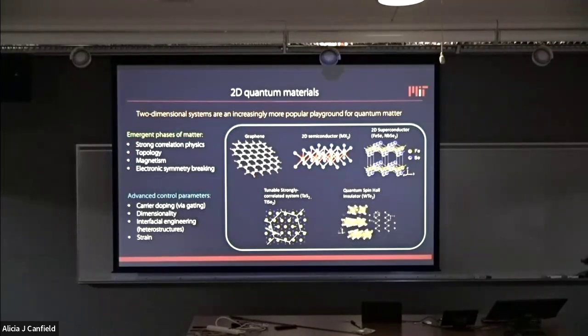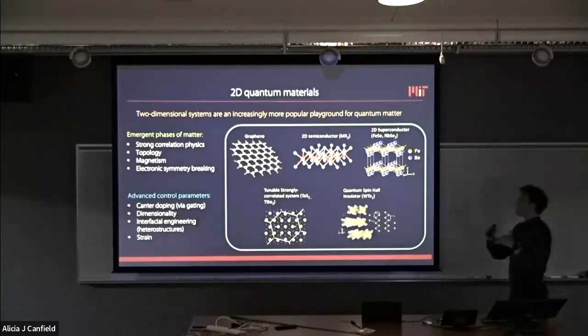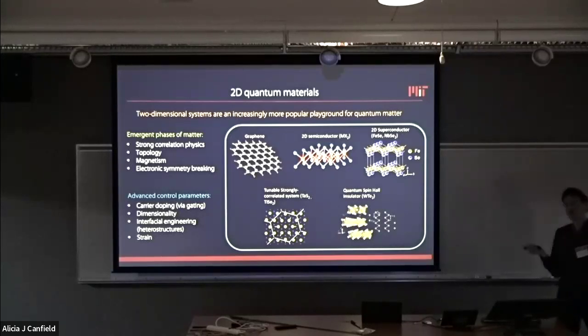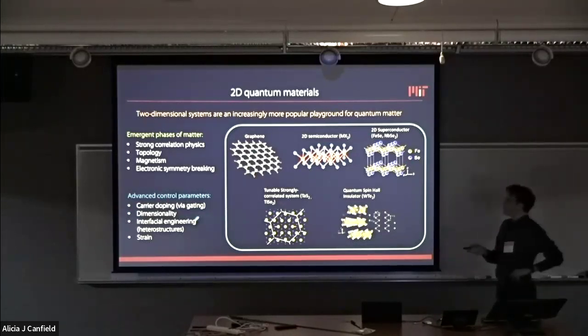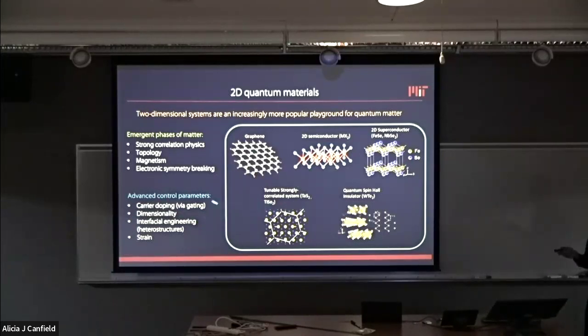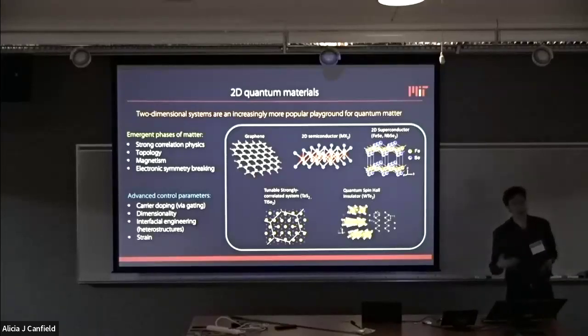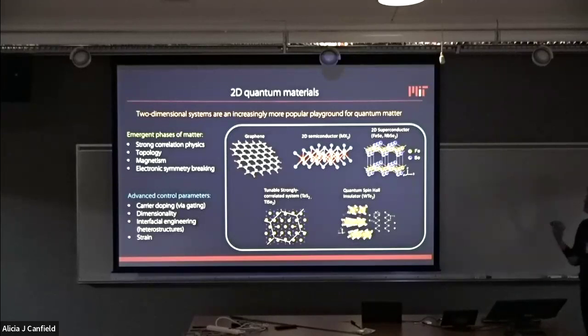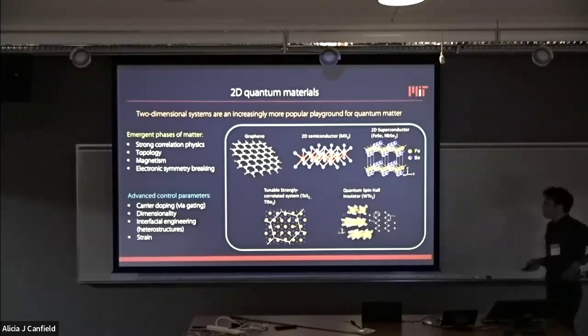There's a lot of structural and chemical diversity in 2D materials, which is great. Another great thing about them is that you can stack them on top of each other, so you can create artificial or synthetic quantum materials where you have interfaces between different materials that you cannot create otherwise in bulk or even with thin film synthesis. And this is thanks to the fact that you're not really bound by the rules of lattice matching in these systems. And so in terms of control parameters, there's dimensionality, there's interfacial engineering, strain. Some of these are peculiar to 2D materials and heterostructures, but one of the most important ones is actually carrier doping, which in many of the systems can be realized electrostatically. So you make microelectronic devices, and then you can study electronic phase diagrams using carrier doping, or using gate voltage to change the carrier concentration, which is great.